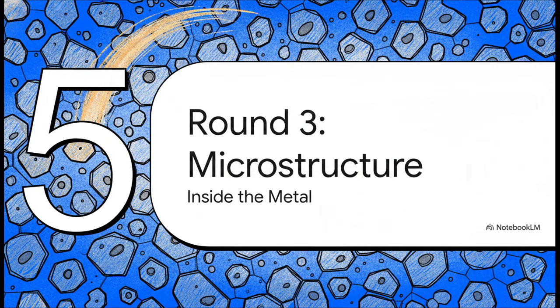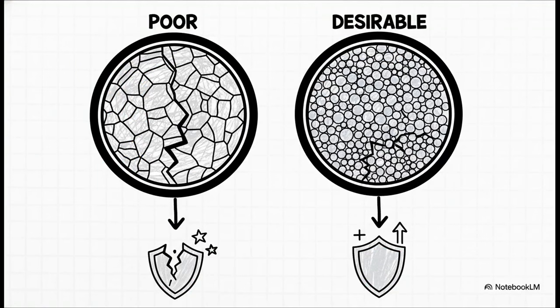The final microstructure. After the welding is done, the arc is off, and the metal has cooled down, what does the grain structure inside actually look like? Because this, right here, is what ultimately determines how strong and tough that weld is going to be. So why should you care about grains? Well, in metallurgy, a good rule of thumb is that smaller is almost always better. A fine, uniform grain structure gives you better strength, better toughness, and makes the weld much more resistant to cracking.